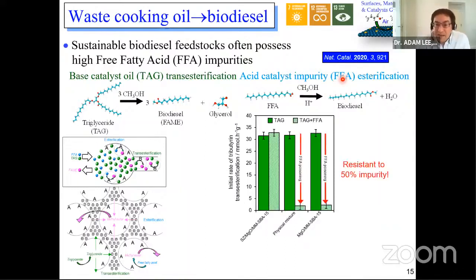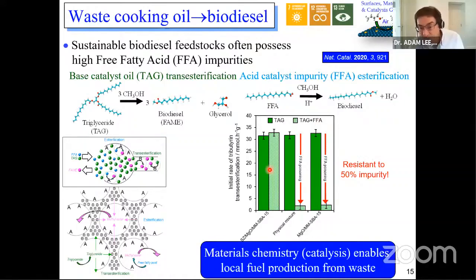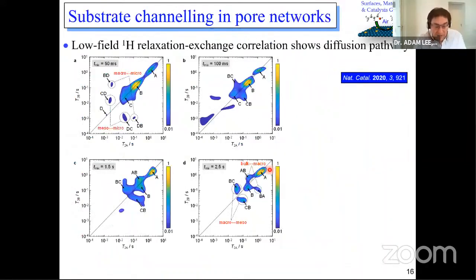Well, the answer is that our catalyst is still just as good, no change at all. However, a pure base catalyst is dramatically poisoned. It can no longer perform because these fatty acid impurities neutralize the base. So a physical mixture and a pure base catalyst perform very badly when you have free fatty acid impurities in your feedstock. However, the spatially orthogonal catalyst just keeps on ticking over. It works very well. And I'll just finish by explaining how this is.